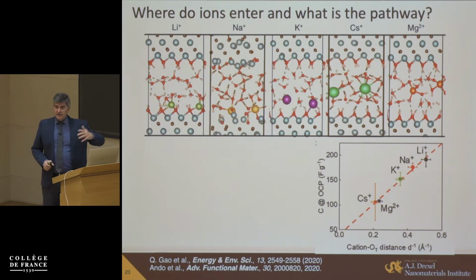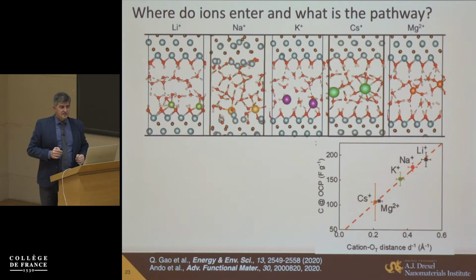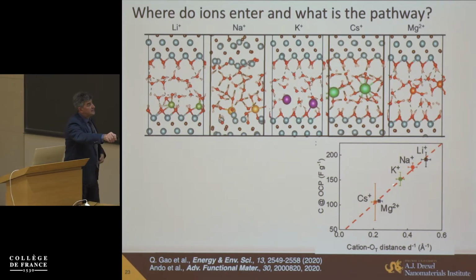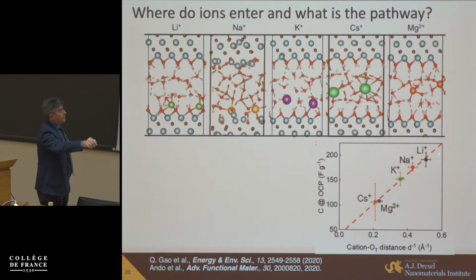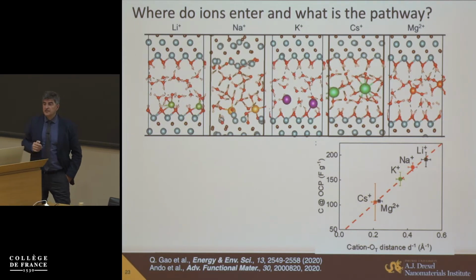Now, even if you intercalate different ions and you know whether they bring or remove electrolyte, they also behave differently. Similarly, we can take several single-valent ions, from cesium to lithium. But you see the capacitance charge stored will be very different. Lithium, sodium will give you much more than cesium, but they all have actually single charge.